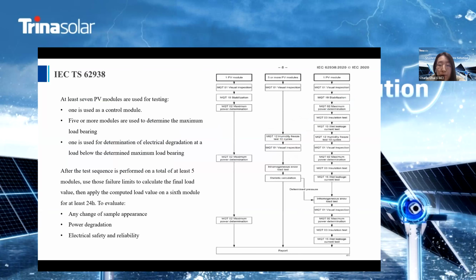and the corresponding standard of non-uniform snow load test is 62938. To test, at least 7 PV modules are required. One is used as a control module. 5 or more modules are used to determine the maximum load bearing. They only go through humidity-freeze 10 cycles and inhomogeneous snow load test. One is used for determination of electrical degradation at a load below the determined maximum load bearing, which goes through a whole characteristic of measurement.